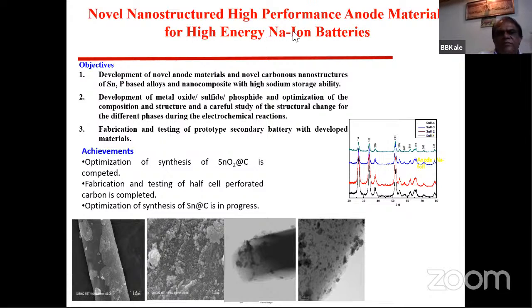So we have a full-fledged sodium ion battery group, and they are working on tin-based anode as well as silicon-based anode, silicon tin-based anode. We started doping with carbon and with phosphorus, because the stability of SnO2 is very low. Though the theoretical capacity of SnO2 is very high, we need to sort out the problem of capacity fading. So we are working on that.